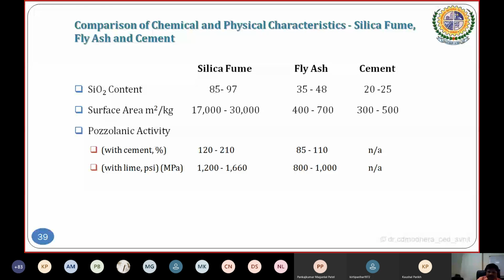Cement is again a different value for the high strength silica fume concrete. If we are using up to say 1200 days, then again you can elaborate and visualize the graph. Here cement content is very high, 564 kg per meter cube. Silica fume is around 89. The water cement ratio, meaning cement binder ratio, combined cement plus micro silica, is 0.22. I think this is an observation available from one of the research scholars.